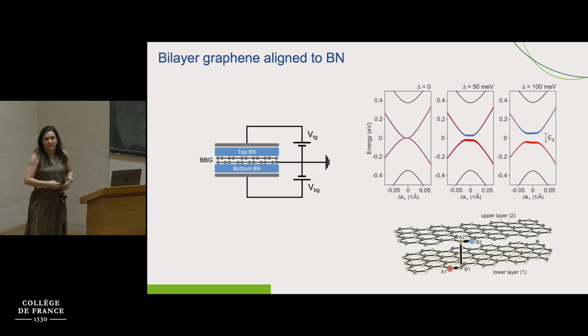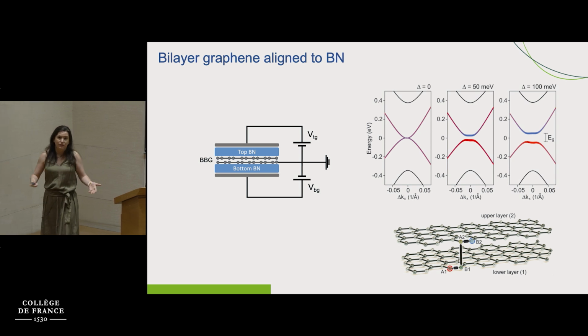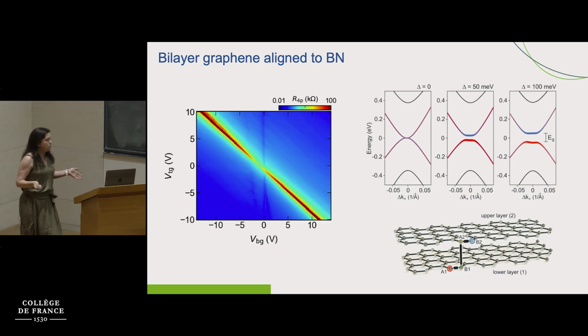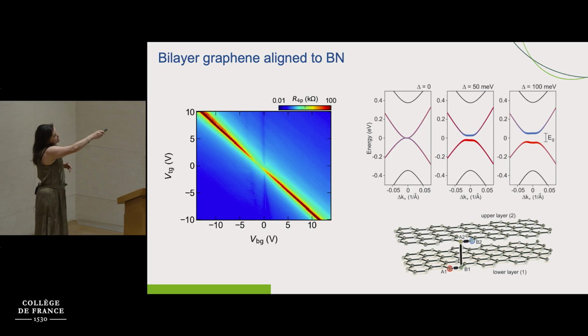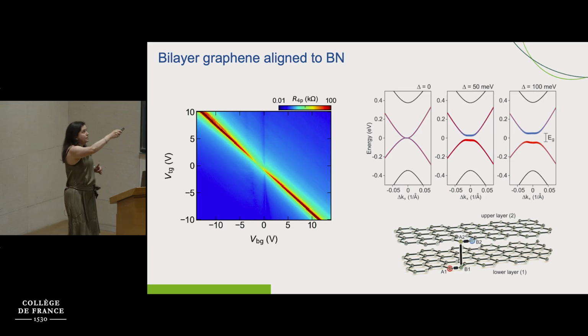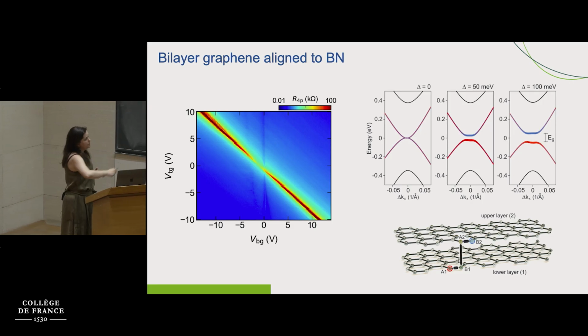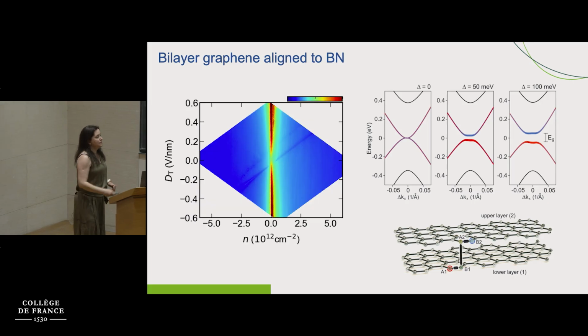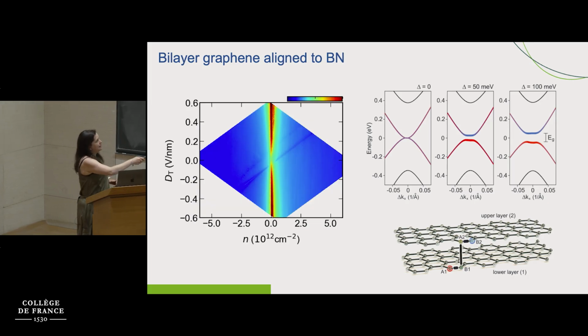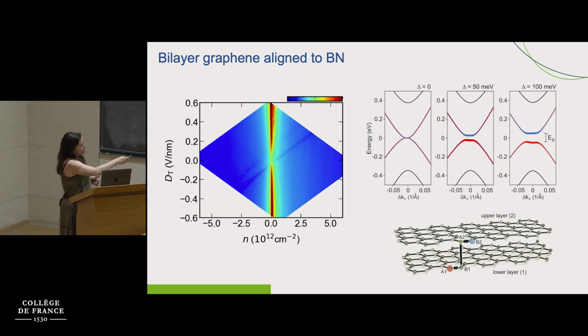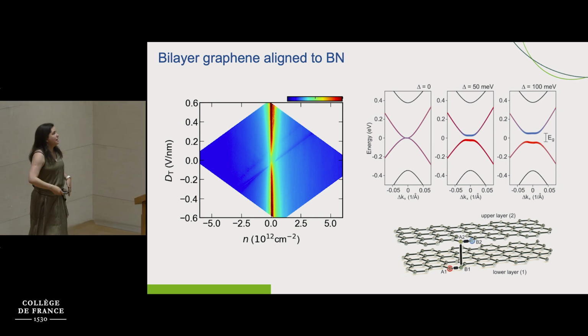The way we tune this displacement field experimentally is by having 2 gates, by applying 2 voltages to the system, okay? So this is a real measurement. Here you can see that the resistance increases, decreases, and increases as I change the 2 gates, which means that I'm opening the energy gap, closing it, and opening again. We can replot this as a function of displacement field and density, and we can see that for 0 density, which is the charge neutrality point, we have this energy gap opening and closing.